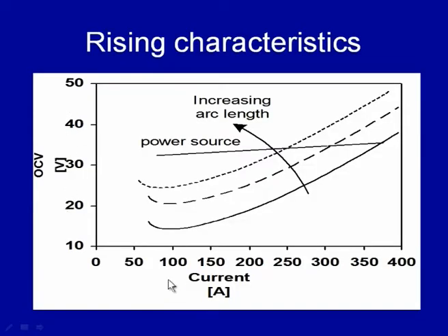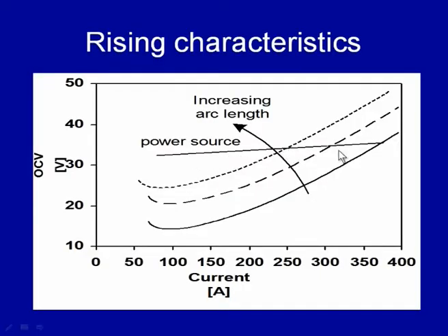So, the typical characteristic of the rising characteristic power sources we will see in this plot. It shows in the y axis open circuit voltage, and in the x axis welding current. We can see that this straight line with the slightly sloping upward is the rising characteristic power source characteristic, and we can see that if we increase the welding current, there is very marginal increase in the arc voltage, and this type of the characteristic power source are important for those welding processes where it is strictly required to have the constant voltage.